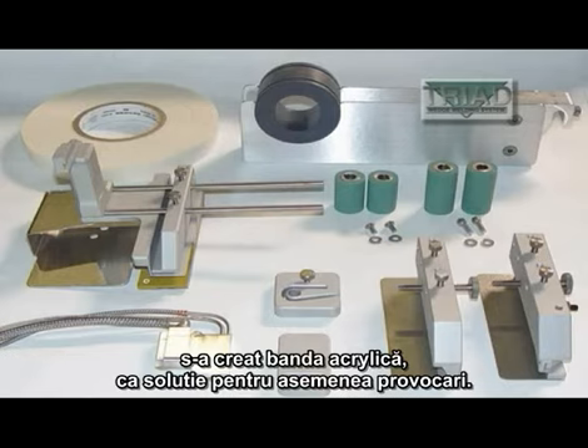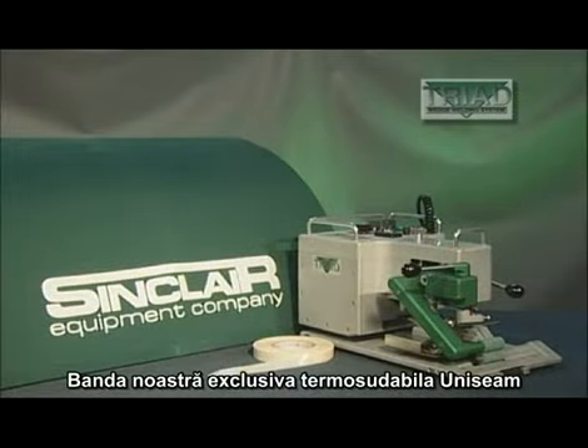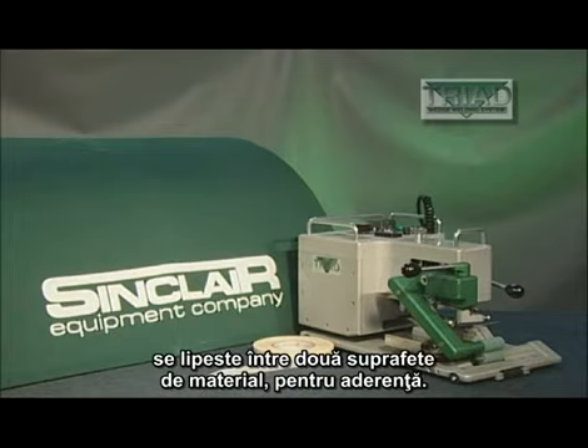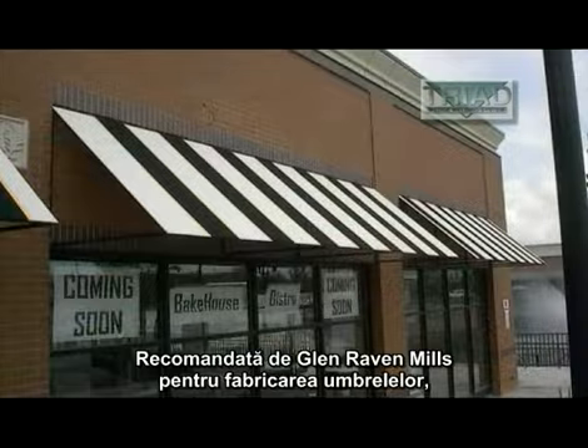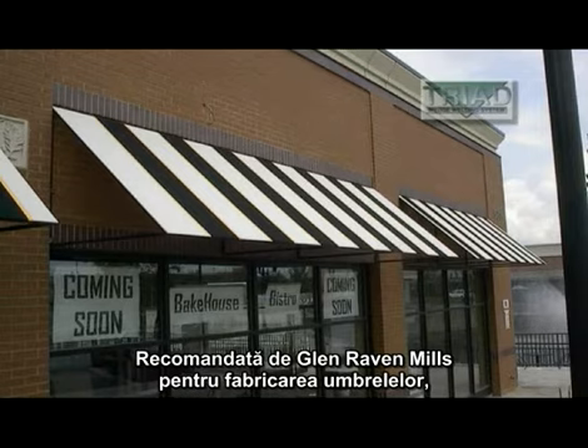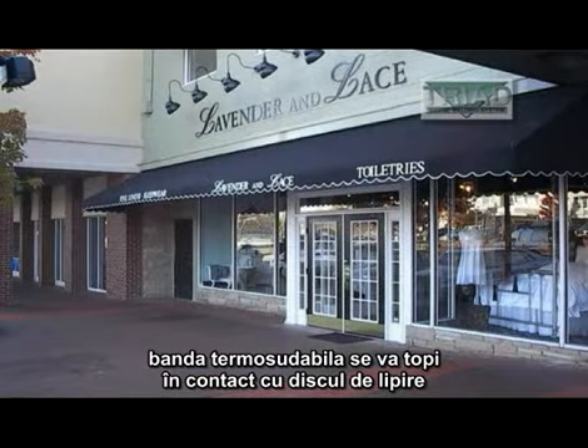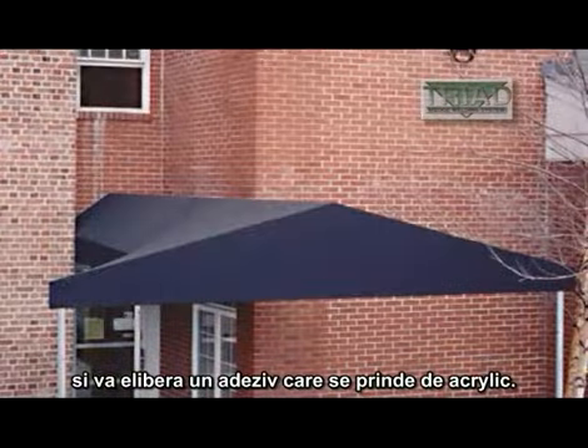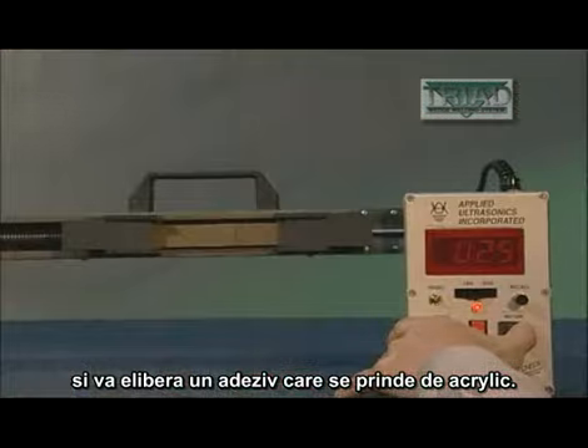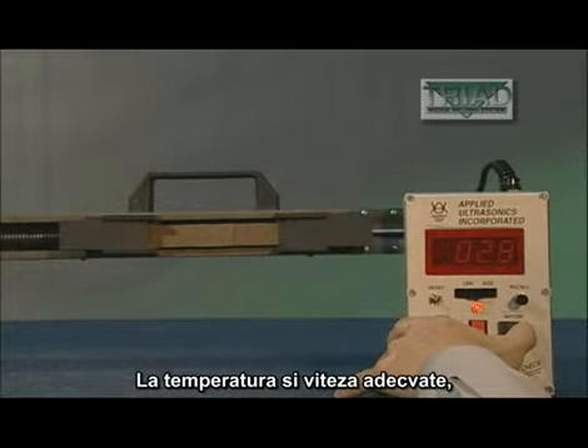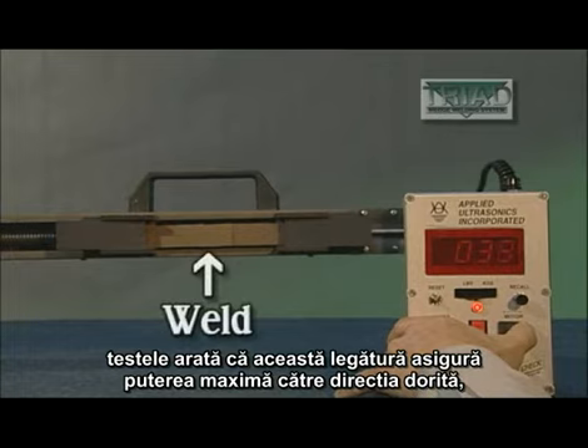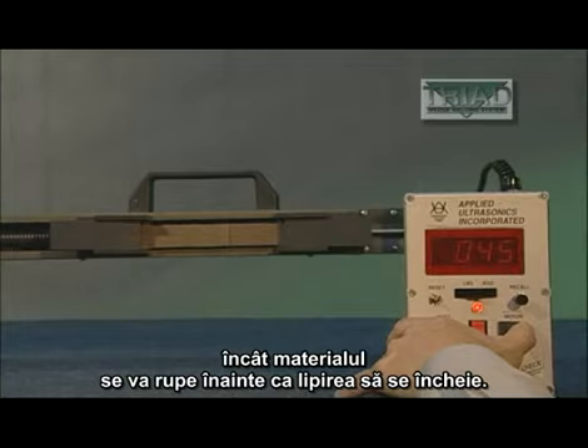solution to these challenges. Our exclusive Uniseam thermal bonding tape is welded between the fabric surfaces to make for the adherence. Recommended by Glen Raven Mills for use on Sunbrella fabrics, the thermal bonding tape will melt with contact to the hot wedge and release an adhesive which bonds to the acrylic fabric. With proper temperature and speeds, tests have shown this bond provides maximum strength in the shear direction to the extent that the fabric will tear before the weld breaks.